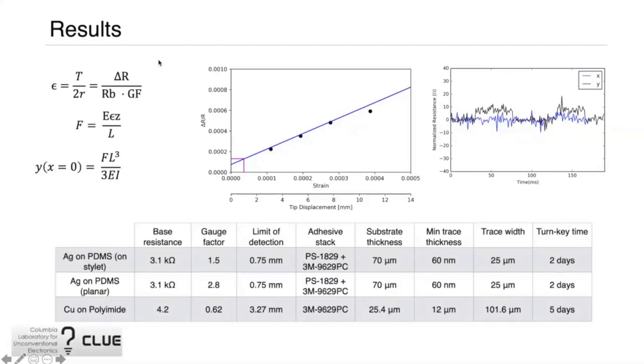To characterize the system, the change in strain gauge resistance was related to bending induced strain. So by knowing the change in resistance and the gauge factor of the device, the bending induced strain can be calculated, as seen in this first equation. From there, the applied force and tip displacement of the stylet can be calculated. And so the only thing we need to know is the gauge factor.